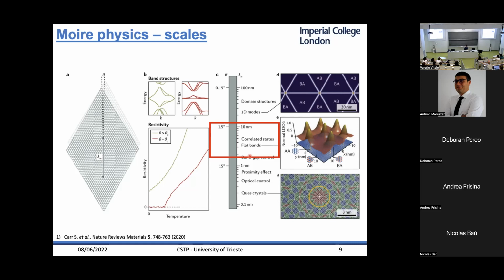And the thing is that at large angle, the two layers are almost uncoupled. In this regime, there is a strong coupling, but not as strong atomic relaxation. Whereas if you go down with the twist angle, then atomic relaxation becomes important, and we have these effects of systems that want to basically put all the strain in these kind of solitons on the structure. So you get these very large regions with one single stacking again, and very small regions with all the strain in.